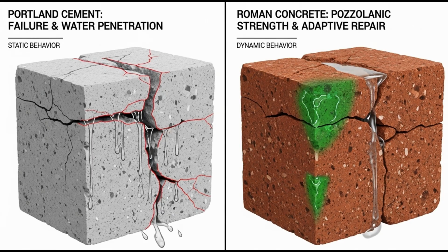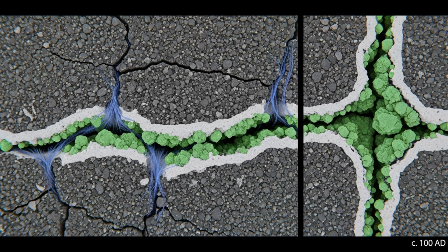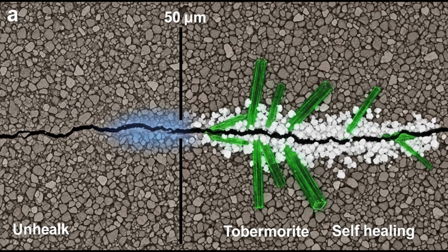Roman concrete reacts with nature. The Pozzolanic reaction continues indefinitely given moisture. Cracks that form allow moisture in. The moisture triggers more Pozzolanic reaction. The crack heals.